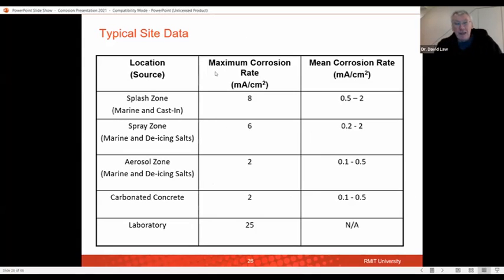And these are the sorts of things that we see when we actually go and measure this on structures. And we've done a lot of work with this. And so we get our corrosion rate, and this is what this equates to in microns that are being lost. Actually, that shouldn't be milliamps, but we can then see that we get our maximum corrosion rates, our highest, in that splash zone. In carbonated, they're down at about 2. We get a lot higher in the laboratory.